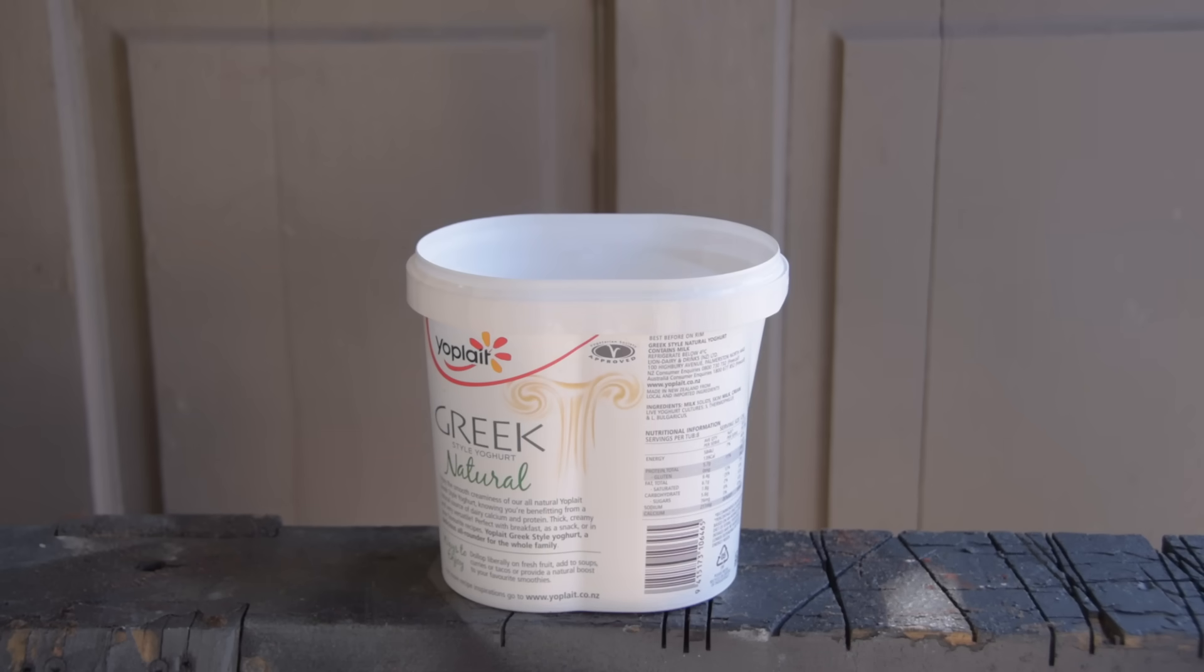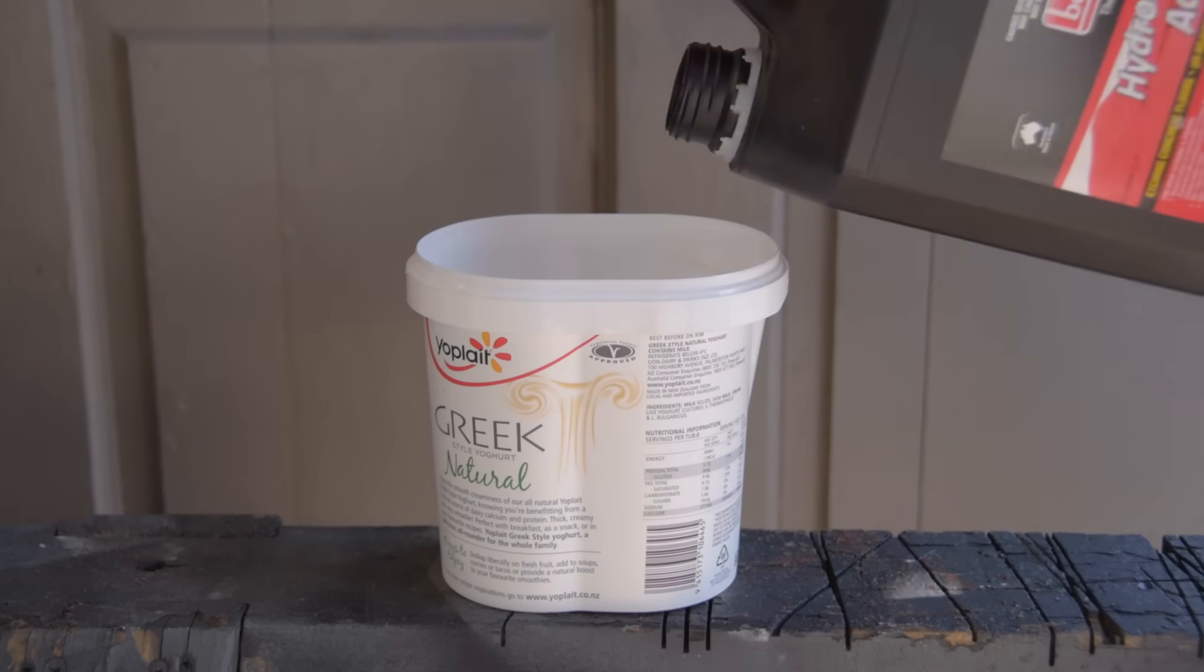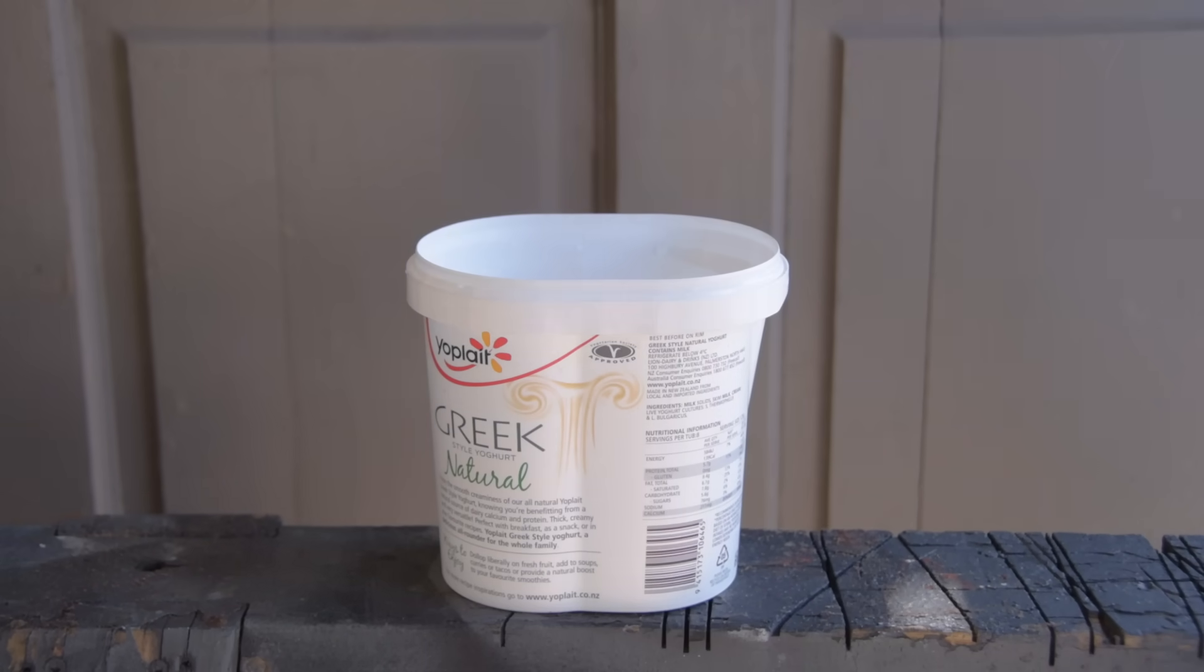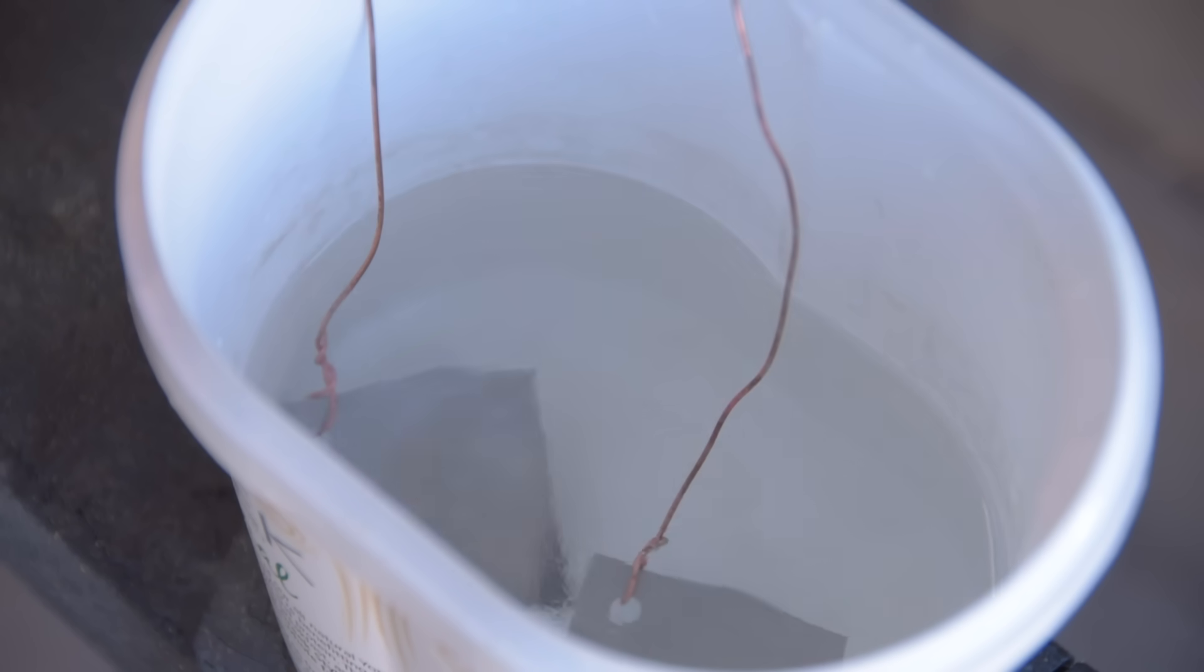Mix about 50-50 water and acid into a natural Greek yogurt container. At a 50-50 mix, I leave my parts in for about one minute.